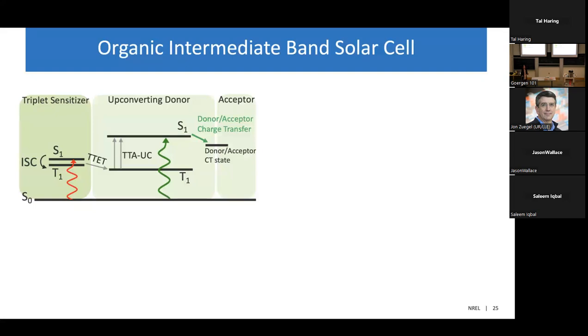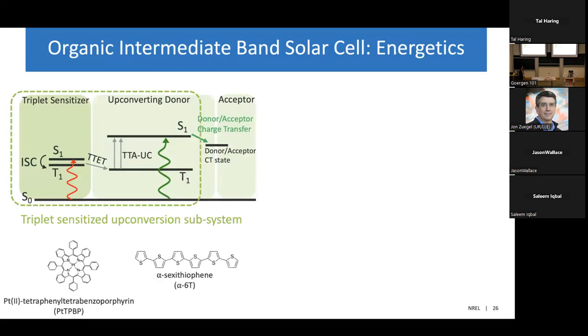So one of the big challenges initially was identifying a material system that would give us these energetic requirements. So we're going to focus on this triplet sensitized upconversion subsystem first and ignore the acceptor for a second. And the sensitizer we identified was PtTPBP, which is a porphyrin compound with a platinum atom at the center. And because of this heavy atom, it can induce intersystem crossing with high efficiency. And then the upconversion material is alpha-sexithiophene, or alpha-6T.